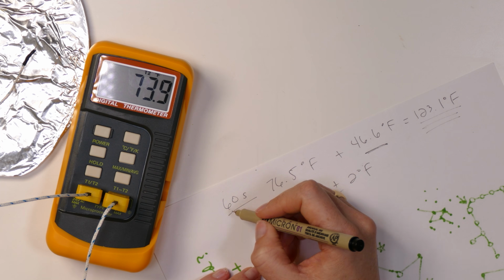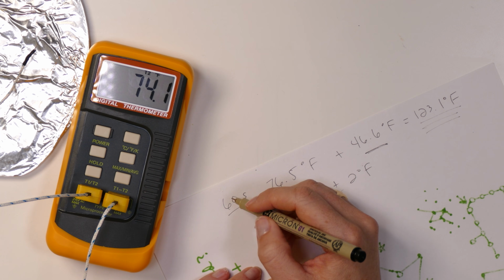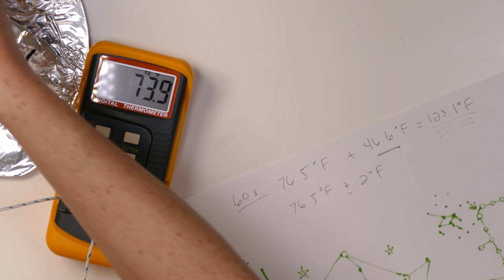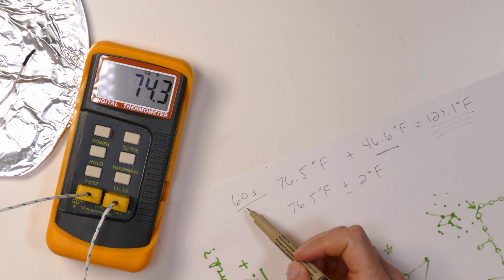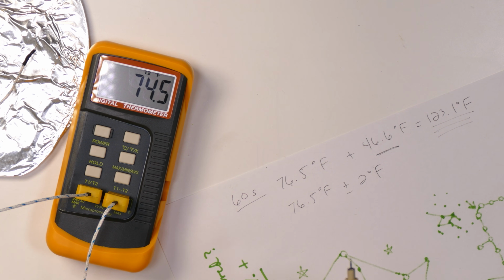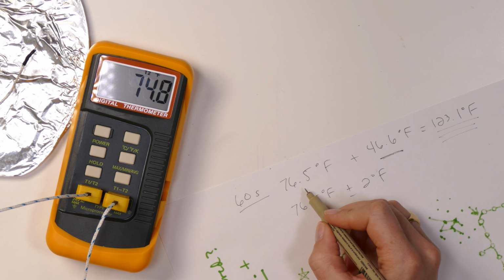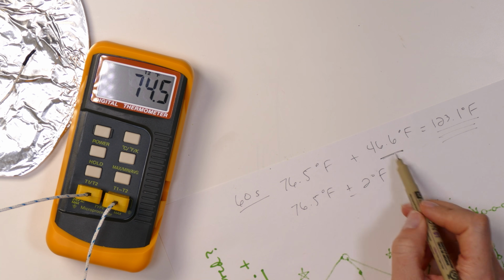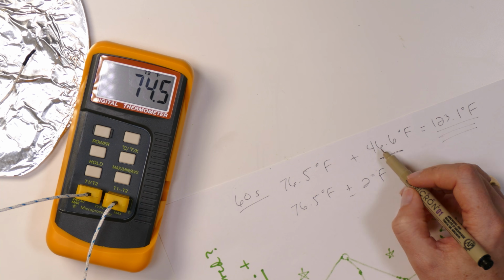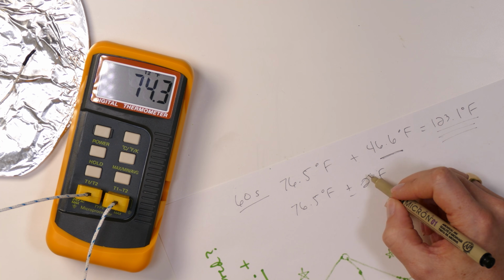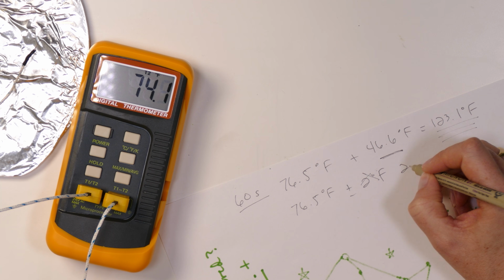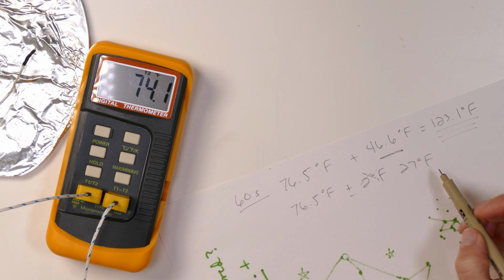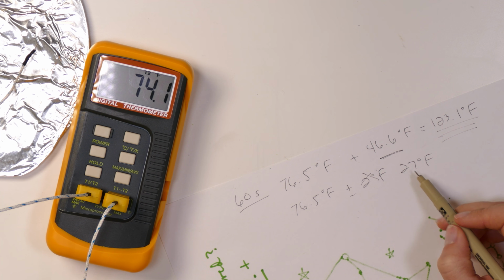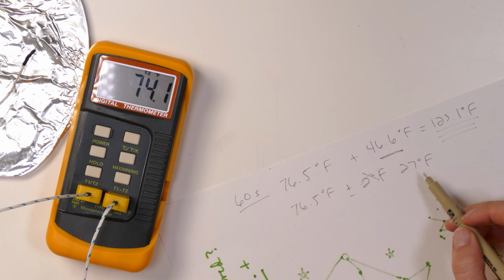So this actually also tells me something else, which is really important, which is my Cocoist Infinity lamp can successfully cure this brand of gel in 60 seconds, which is awesome. Now, if I changed this curing time to 30 seconds, this whole scenario might not have happened. Maybe this did peak at 46, but maybe this actually peaked again at 27 degrees or something like that. So that would tell me that there was still a little bit of curing that needed to happen even after 30 seconds of UV exposure in that particular lamp.